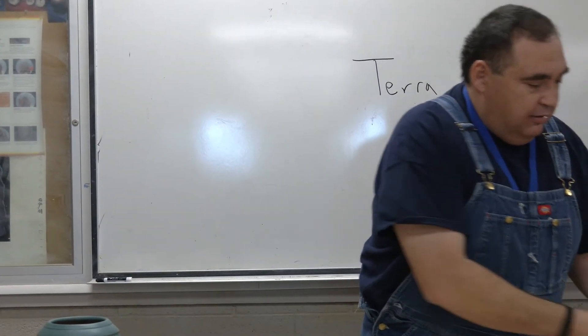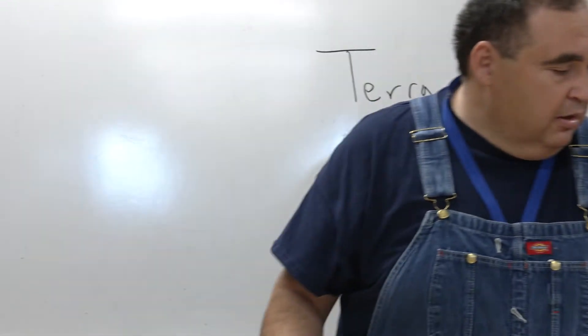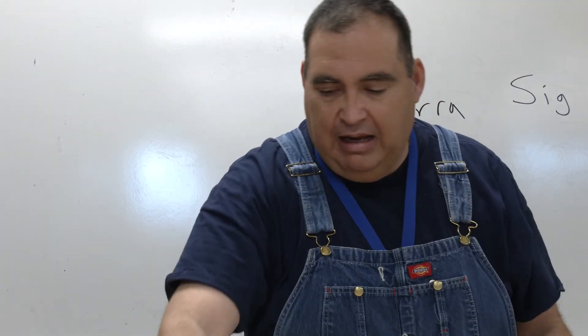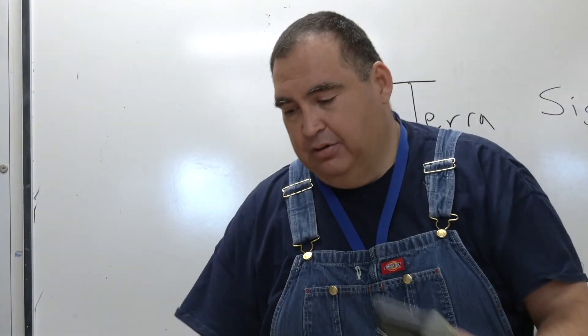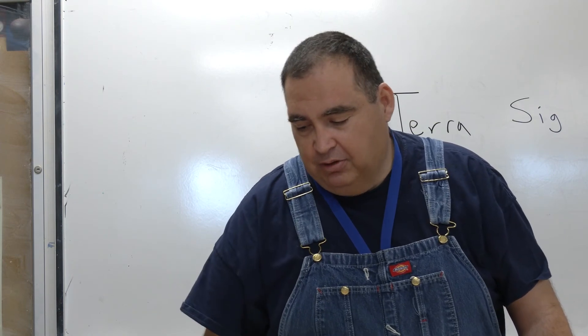Over here I have feathers that I'm going to test to see how much of a mark appears with the feather or the carbon. I have emu feathers, which is what's on this piece — that's what made these lines that look like ferns. I also have horse hair, and that's what makes the black lines. By putting these on the piece in the temperature range — usually 1100 to 1300 degrees — I have a thermal heat gun that I check to see how hot the piece is. Right now it reads 63 degrees on the surface of this piece. When I'm firing, I check the surface: if it's too hot the carbon won't stay; if it's too cold, when you wash it, the carbon will come off. So timing is important.